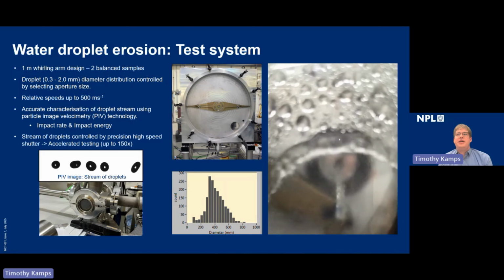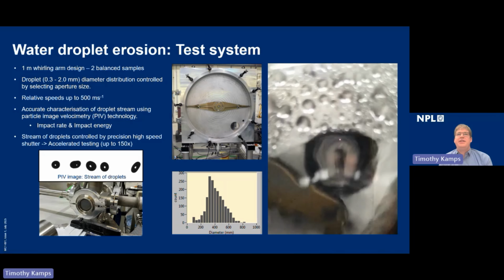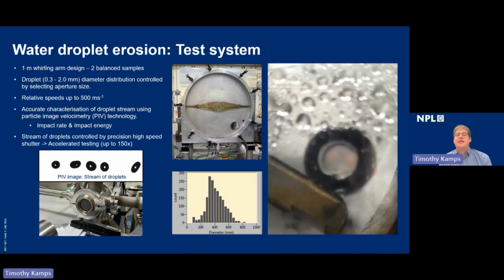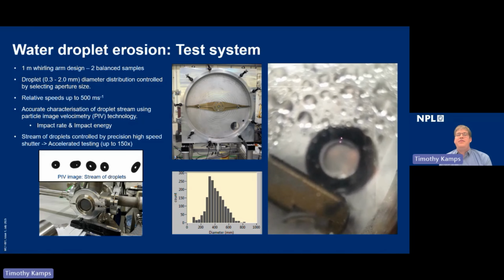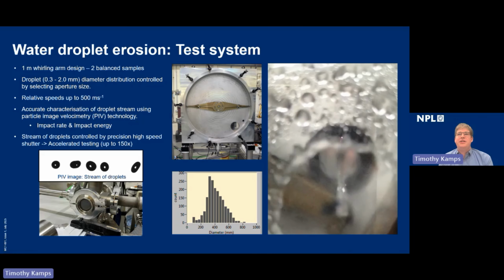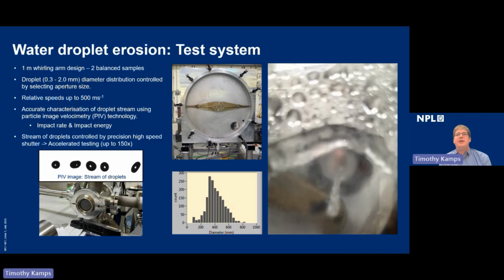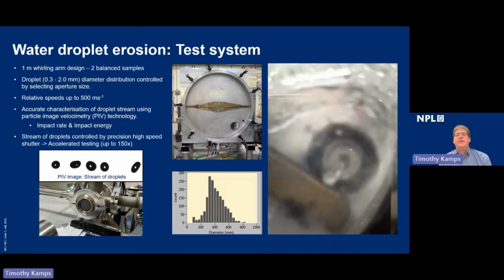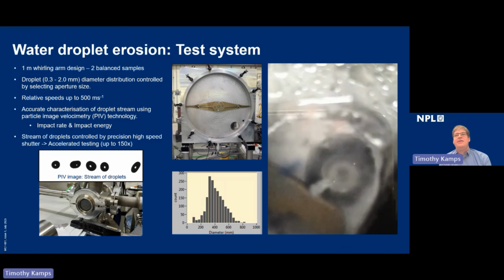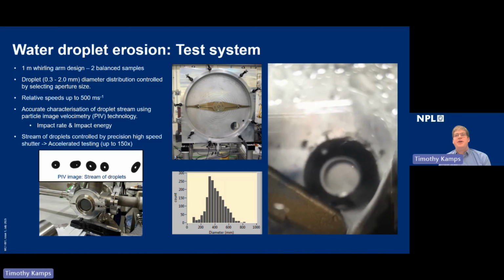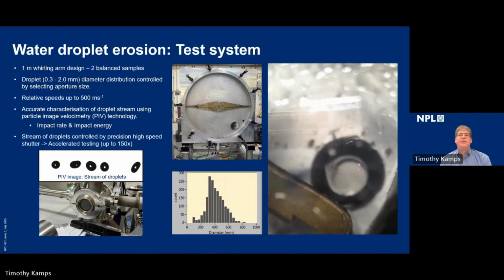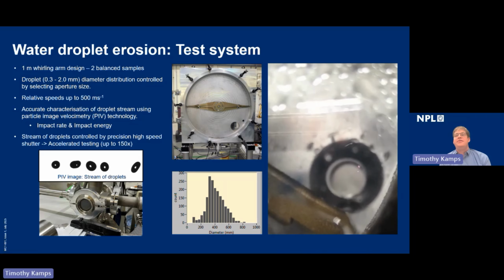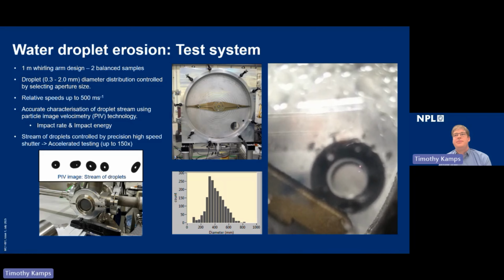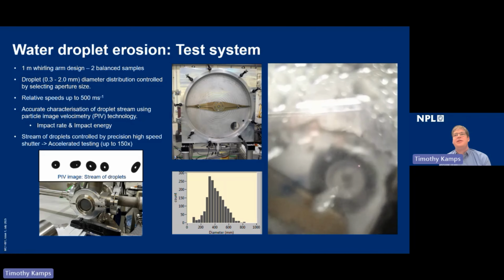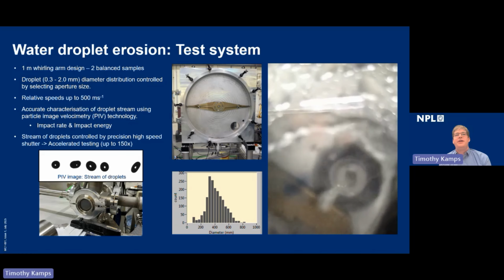Because our rig is a rotating arm rig, it offers the ability to accelerate the testing of samples by over 150 times. And because of this, if we want to test in quite mild conditions, we need very precise timing of the droplet stream. And what you can see on the right-hand side is a video of the droplet stream emerging into the test chamber and being controlled by a sluice gate. The first time you saw it was at real speed, and the second time was at 30 times slower than real life.